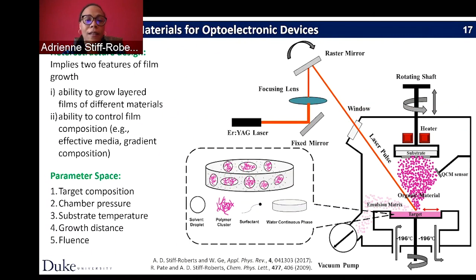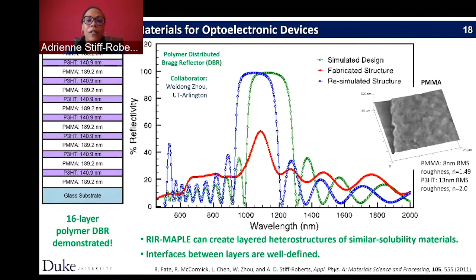So we have been able to demonstrate some cool capabilities of MAPLE as a result of this technique. Here we're showing a distributed Bragg reflector, and this is actually work that I did with one of my former group mates in the Bhattacharya group at the University of Michigan. Wei Dong, my collaborator, designed a distributed Bragg reflector in the green. It was based on 16 repeat layers of 2 different polymers, P3HT and PMMA, and they had a particular thickness and a particular refractive index. If you have these stacked layers, because you're controlling the reflection and refraction at each interface, you can create a mirror. So the design was in green.